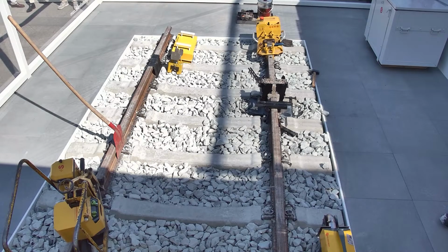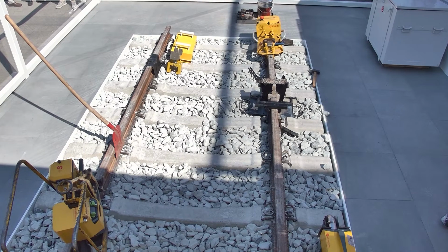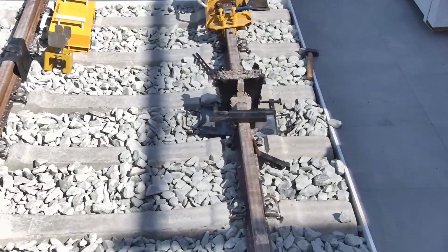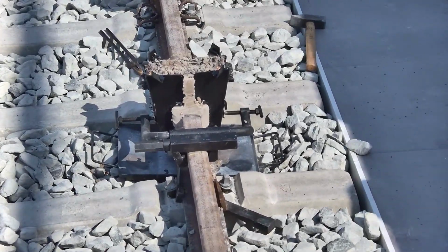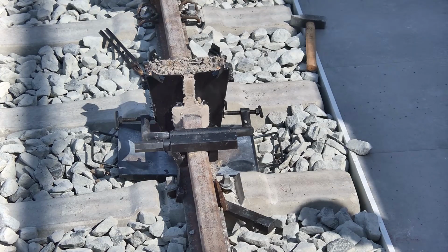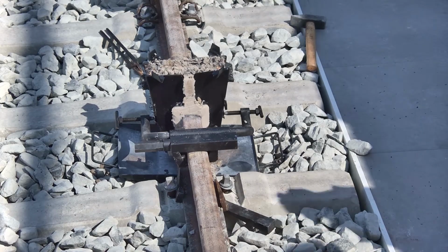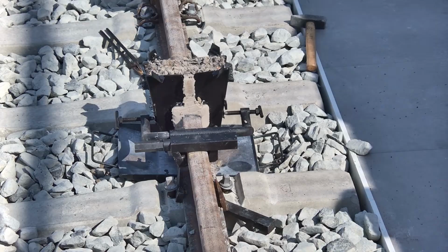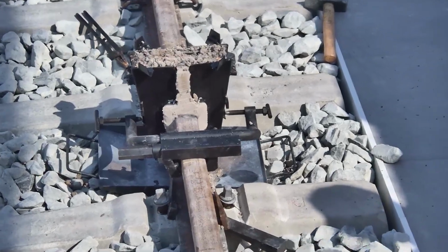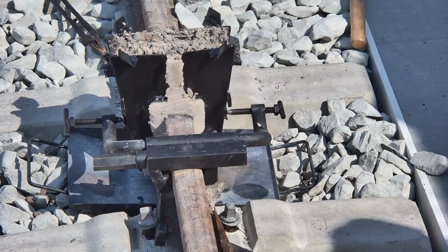What happens now is this solidification of the liquid steel. It first melts a little bit of the rail to create a fusion zone, and then the solidification happens in a predefined way to then create a steel bond that has very precise chemical and mechanical properties. Which is why the heat management is of such importance to make sure that the microstructure of the steel is exactly the microstructure that we intend to create.